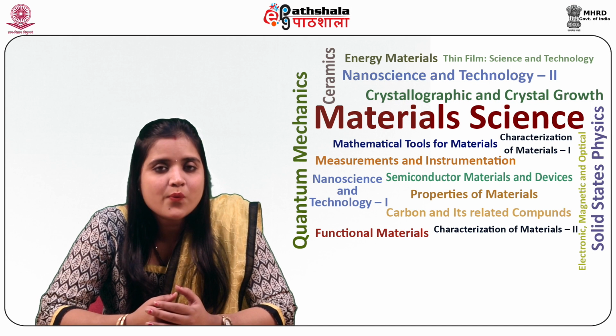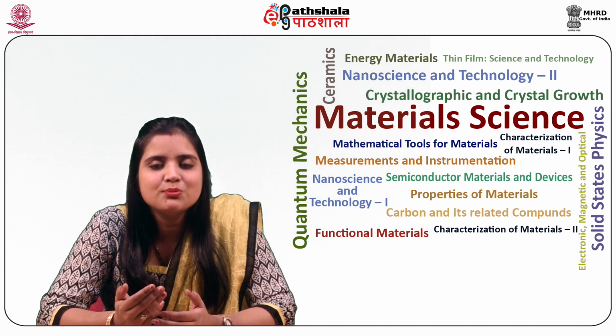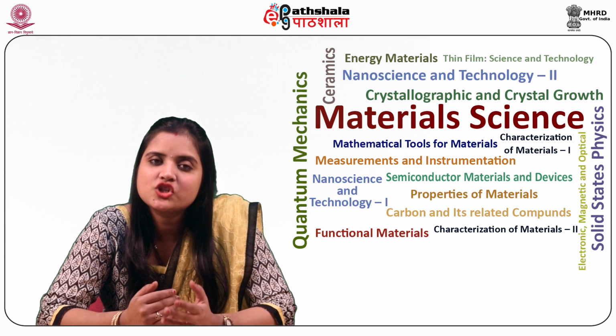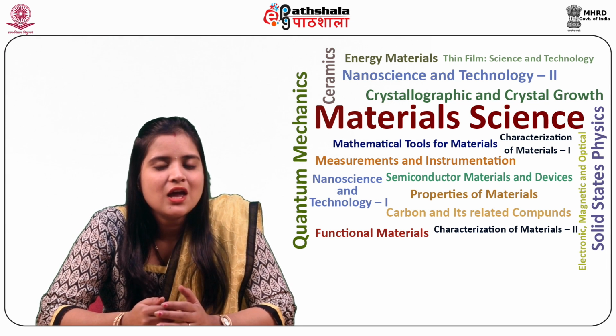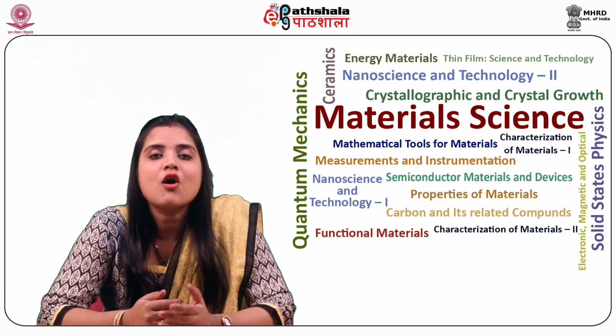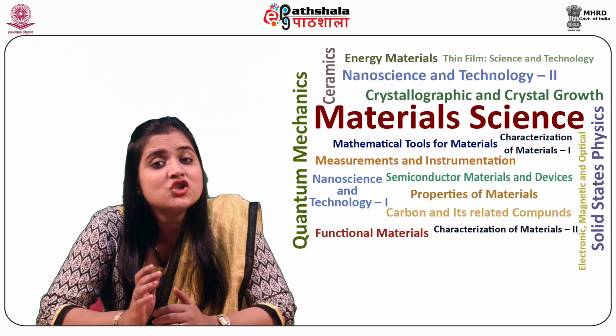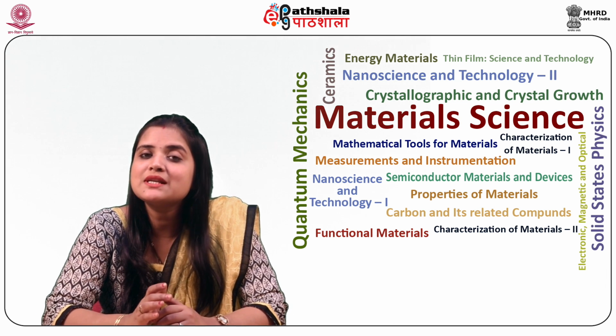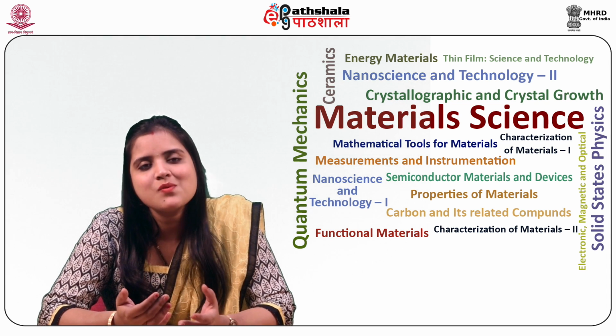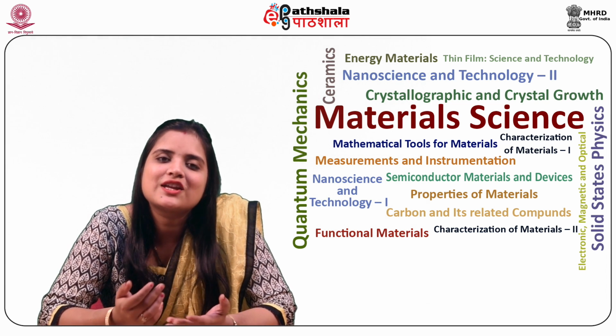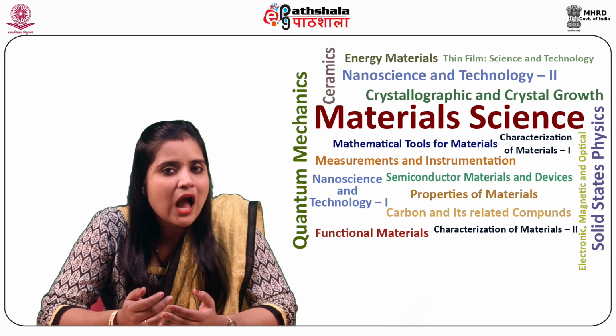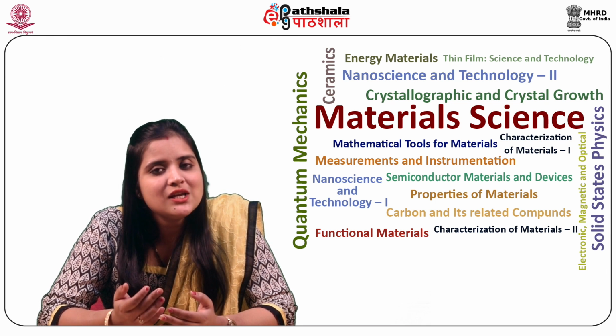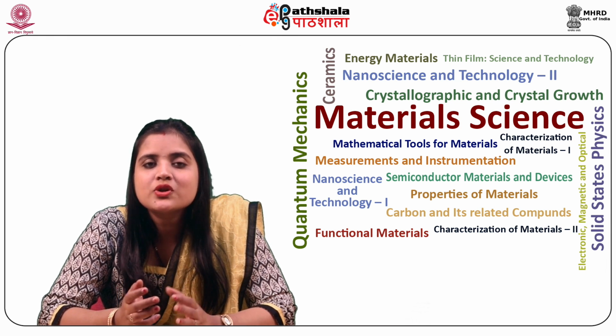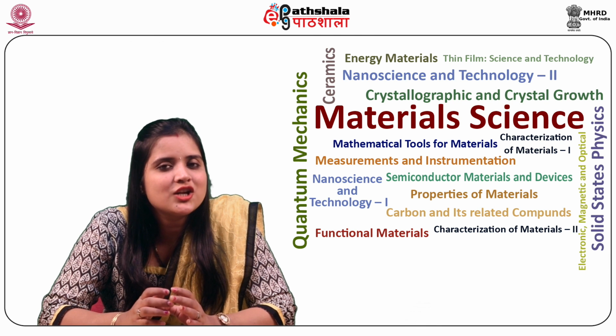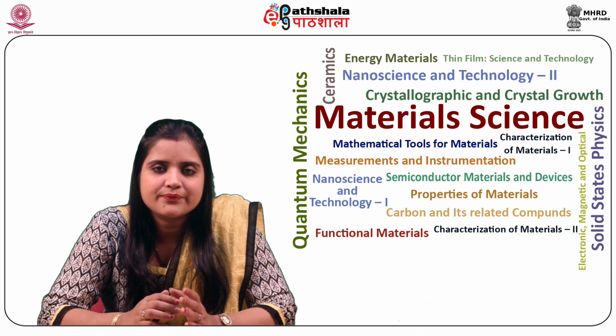In case of very wide distribution of relaxation time, the peak in epsilon double prime of omega, that is dielectric loss, which was represented by equation 5, loses its significance. It is completely masked by almost frequency independent dielectric loss.